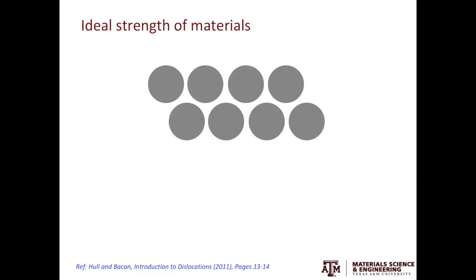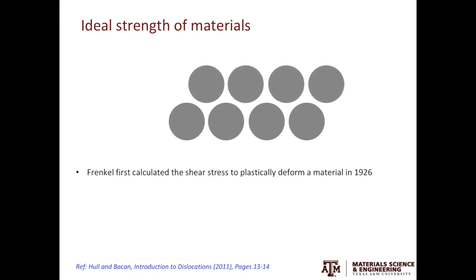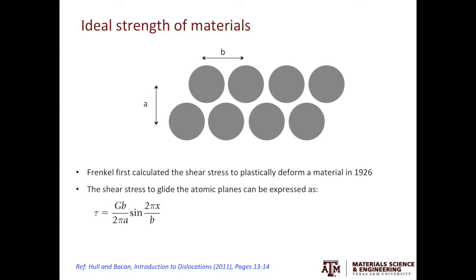Since about 100 years ago, scientists have been thinking about what is the ideal strength of a material — the highest possible strength. The first person who tackled the problem is Frenkel, back in 1926. He argues that to plastically deform a material, you need to glide one atomic layer against another. Assuming the equilibrium distance from one position to another is B, and the two atomic layers are A units away from each other, the shear stress required is described as (GB / 2πA) × sin(2πX / B), where G is the shear modulus and X is the shear translation.